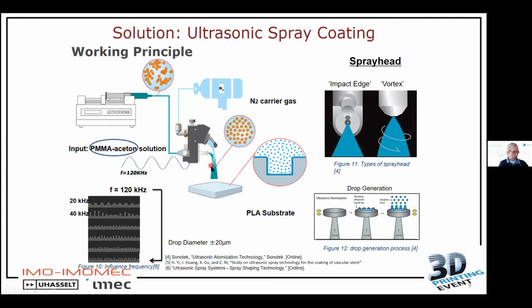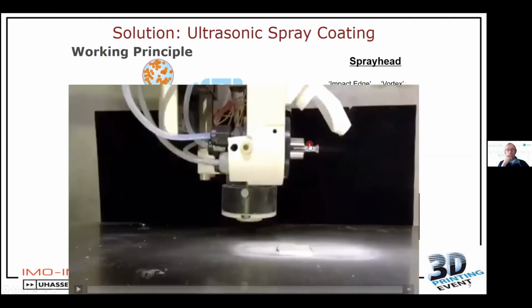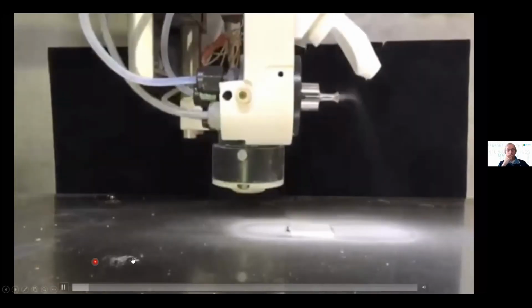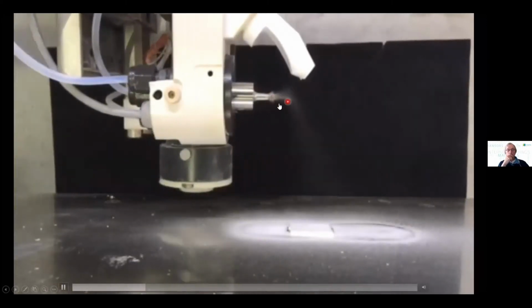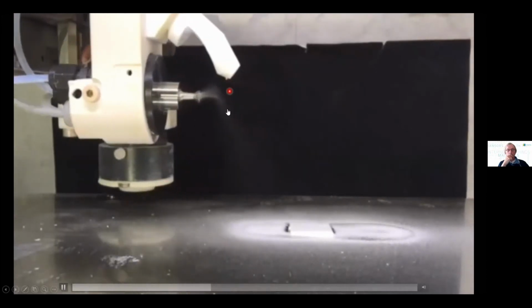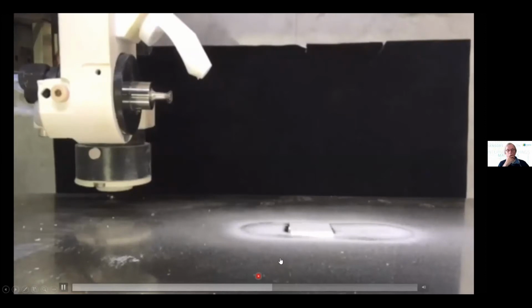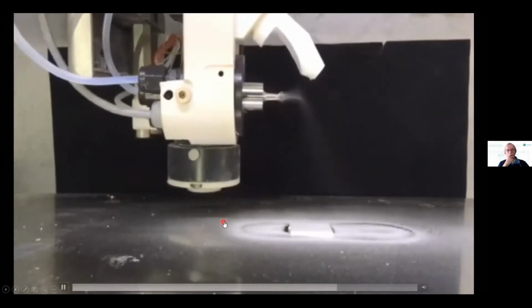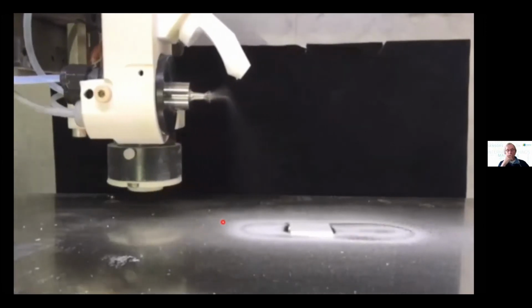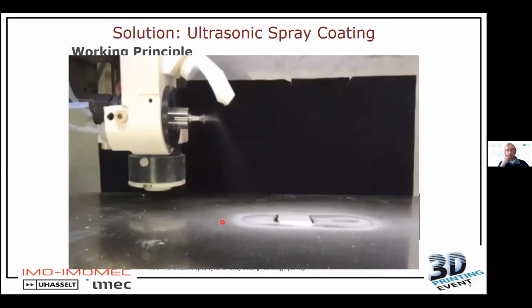And if we want to play with the speed of the droplets arriving at the substrate, you can play with the pressure and the power you apply to the carrier gas. So you can choose to have the droplets arriving very slowly to the substrate, and that's exactly what we would like to use here in this story about 3D print. Here you see a quick animation of the system. Here you see the droplets generated, and here you see the deflector with the carrier gas that brings the droplets towards the substrate. This is a nice technique that is used in our lab, but you can also use it roll to roll in industrial lab.